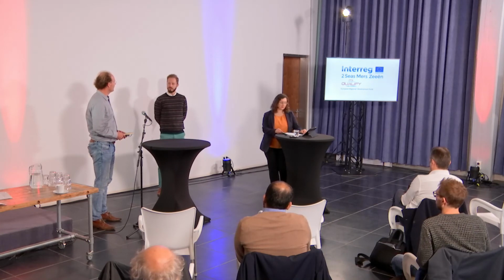The interface model was calibrated with DCB tests, double cantilever beam tests, where the fracture energy was recorded in order to propagate the pre-crack in the DCB test. That energy was then used for a cohesive zone model, that is an interface model that was plugged in between the composite to adhesive interface. And there we used the fracture energy as an indicator for the fracture initiation and fracture propagation.